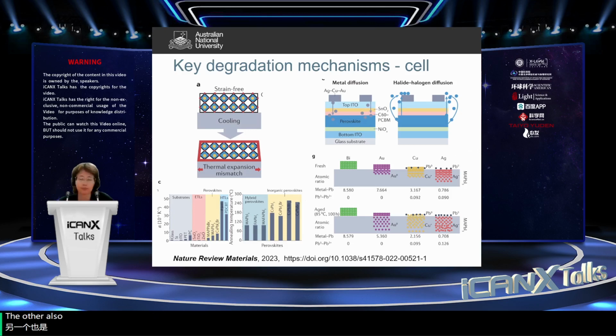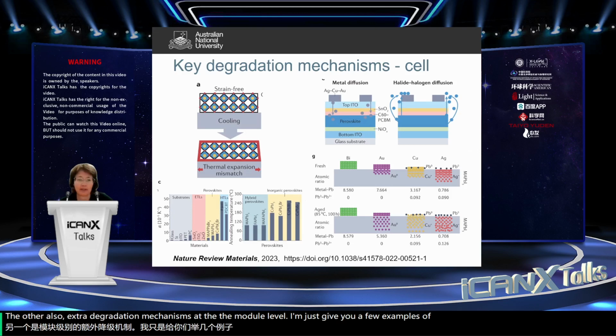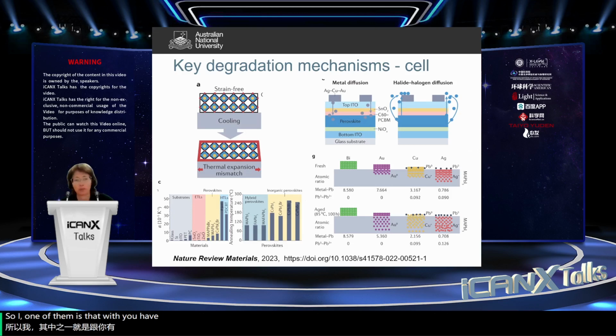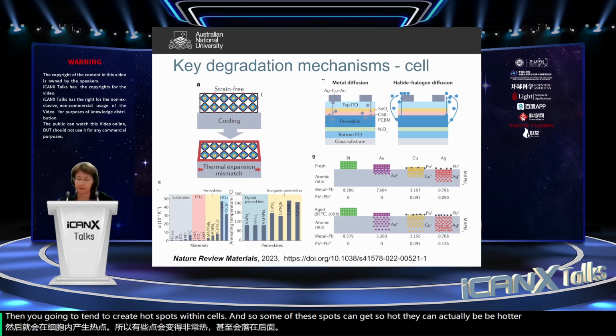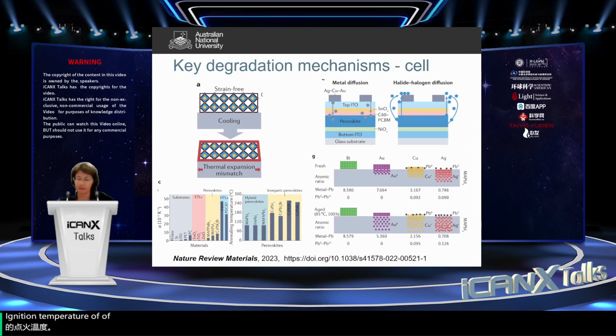Now, there are also extra degradation mechanisms at the module level. I'll just give you a few examples of that. So one of them is that when you have a module, if you partially shade the module, some of the cells will be in reverse bias. Now, if you have some of these cells in reverse bias, and especially if the cell is non-uniform, then you're going to tend to create hotspots within the cell. So some of these spots can get so hot they can actually be hotter than the degradation temperature of the perovskite. So you could get to 120 degrees or so. The perovskite may break down. So reverse bias is a significant issue for perovskites.